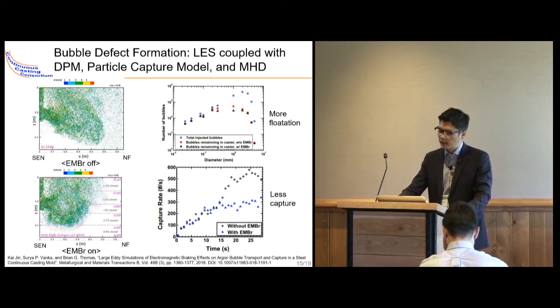We found that with the EMBR, fewer bubbles reach the solidifying steel shell, and fewer bubbles go deep into the deeper region, as shown in the left two figures. So EMBR increased the flotation and reduced the bubble capture into the steel shell. This means fewer surface or internal defects with the EMBR effect.